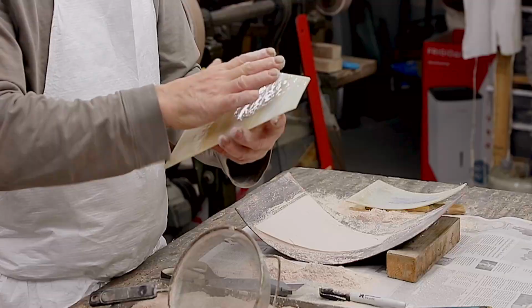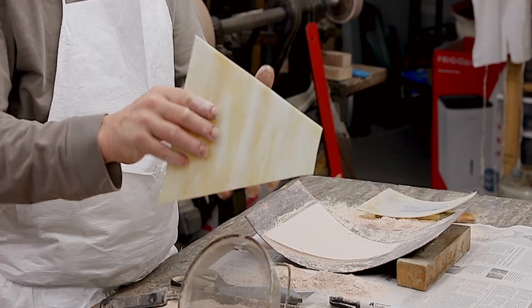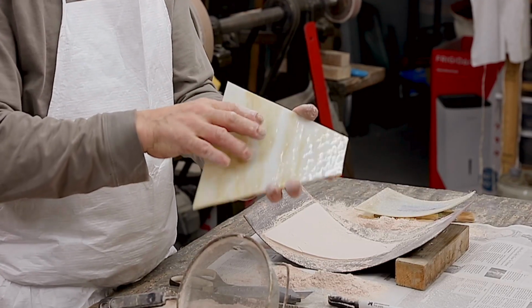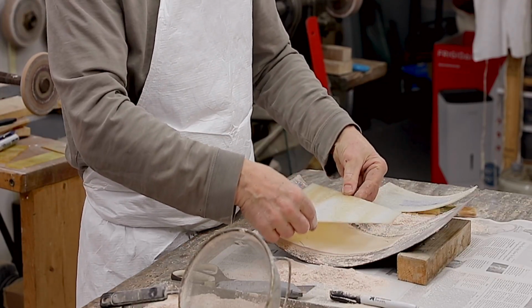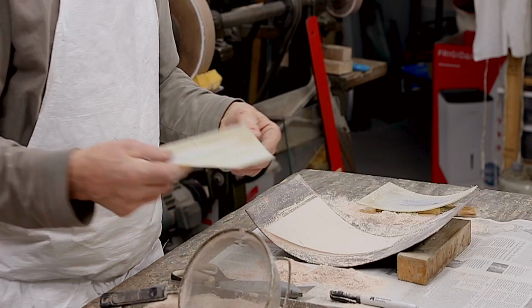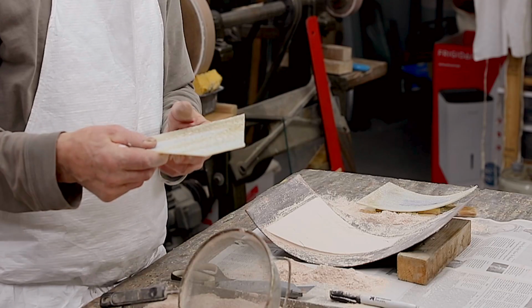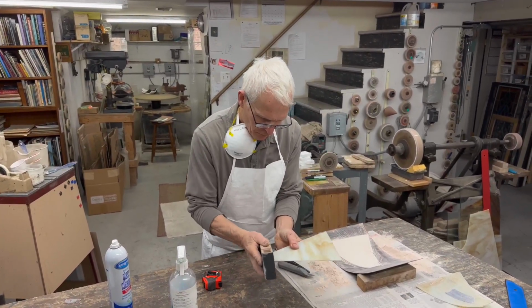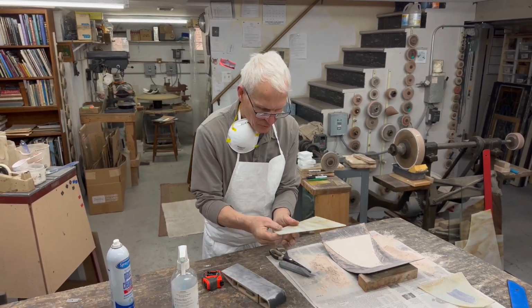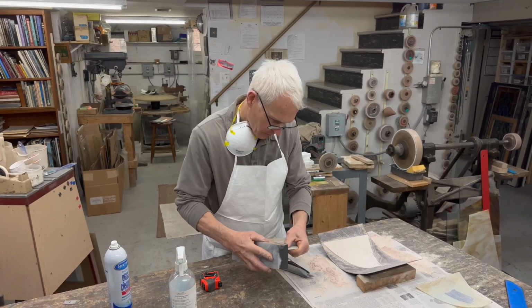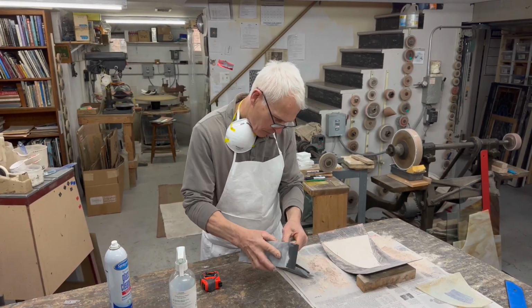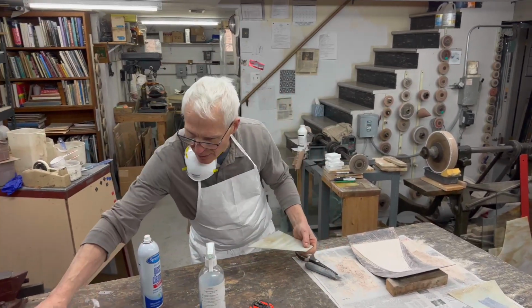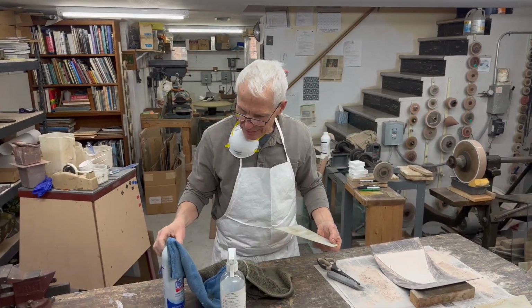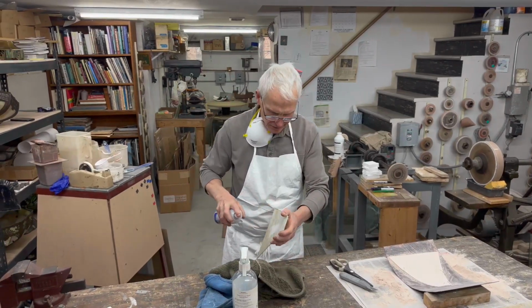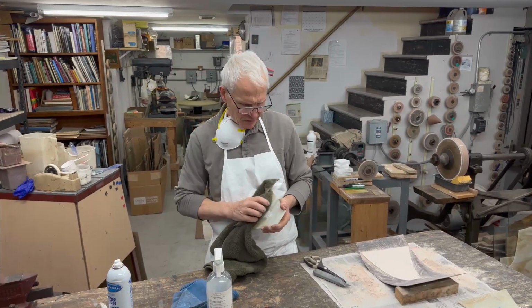I always suggest that people take their glass blank and smooth off the edges so it's not sharp. Then clean the glass thoroughly, put it on the powdered mold, and stick it in the kiln. Take a silicon carbide glass grinding belt, give it a shot of glass cleaner, and try to keep your fingerprints off, for sure, the front surface, the smooth side.